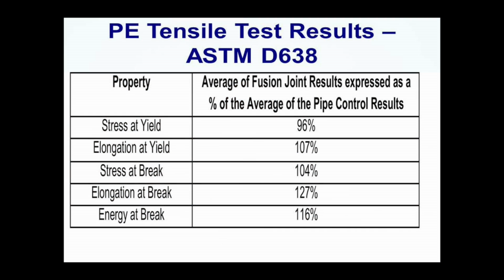So looking at the tensile test results in polyethylene, we looked at the stress at yield, the elongation at yield, the stress at break, the elongation at break, and the overall energy to break. For all of these, you can see it's either just under or just over 100% when compared to the same exact test done on the same exact type of specimen taken from the control pipe. The only difference is the butt fusion had the butt fusion in the middle, the control pipe has no butt fusion, it's just the same parent material without the butt fusion.